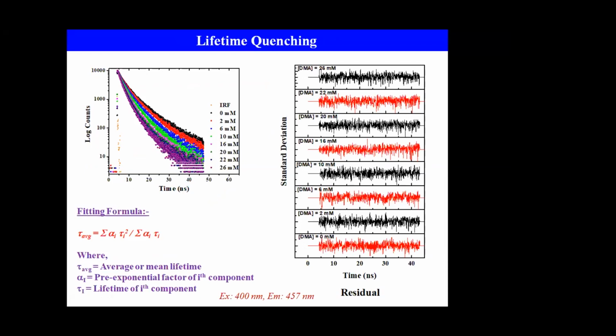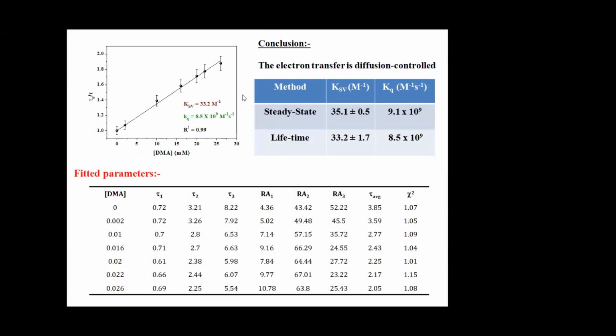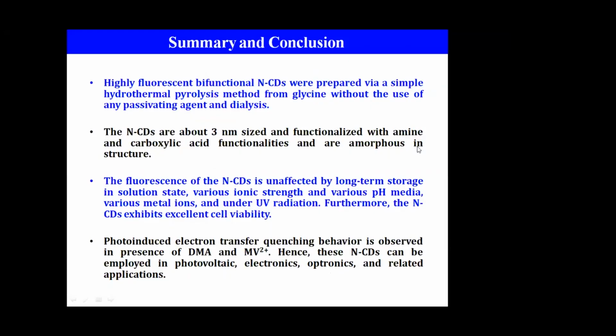And these are all materials, good material for the excited state electron transfer. Out of the 5 materials we have looked at, this alone shows you the excited state electron transfer behavior. These are all because of the nature of the doping and the surface behavior, surface functionalization, that we see is altering the property of the series that we have synthesized. The fitting parameters show what kind of lifetime quenching constant and steady state intensity quenching constant - they're closer, and they're all in the diffusion control limits.